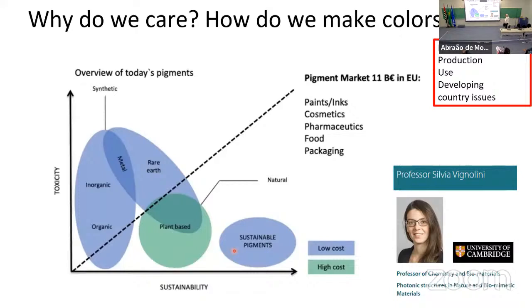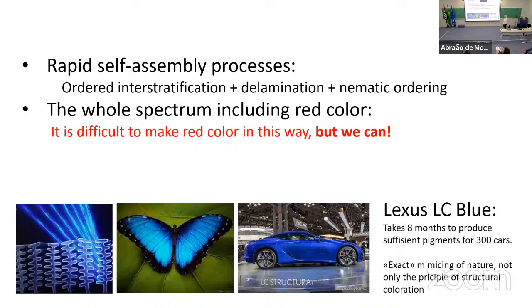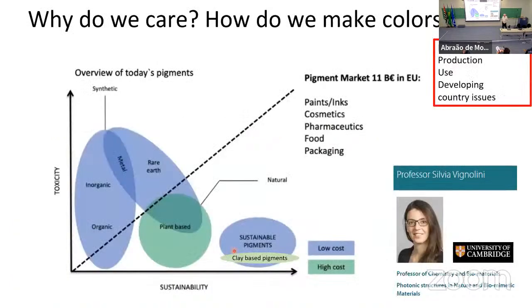Sustainable pigments, that could be the cellulose I mentioned, or it could be our clays. Well, as I mentioned, clays are abundant, they are non-toxic, they are good in this sense. But when I say that maybe these suspensions of the clay layers can make pigments like this, you should say that that's not a good idea, because most of the material in my suspension is water, and only 1% clay. So it doesn't really matter whether the clays are sustainable or not, because only 1%, the functionality, the color comes from the clay, but most of the material is the matrix.